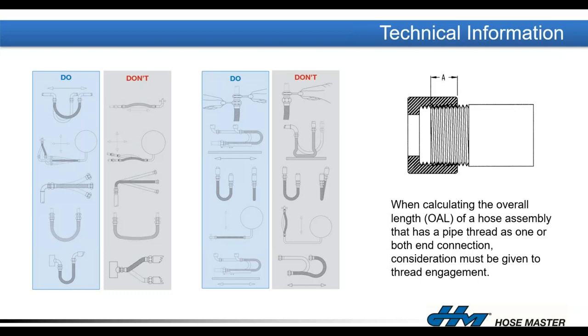One way they can apply torque to that hose is instead of grabbing the hose by the fitting hexes as recommended on that top left-hand diagram or the top blue diagram in the center, they accidentally grab the hose by the braid collar. Very important for corrugated metal hoses to never grab the hose by the braid collar. That will apply all that torsional stress directly to that hose, and it will cause it to crack, and it will leak upon startup. So very important never to grab a metal hose by the braid collar when installing it.